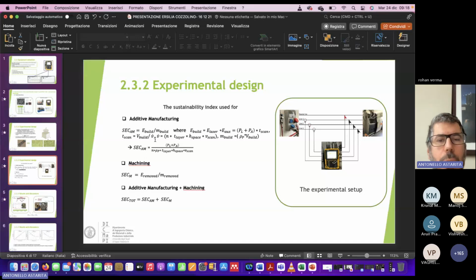Okay. At the end, you can obtain this formula that gives you an idea of the specific energy consumption in additive manufacturing. You have the power required by the laser plus the power required by the auxiliary system versus the number of layers, the density of the powders, the thickness of each layer, the hatch space, and the V-scan. So with this formula, you can easily calculate the specific energy consumption. And again, when you choose the processing parameters, you have to be aware that you are moving inside this formula. So by accordingly choosing the process parameters, you can try to reduce the specific energy consumption.